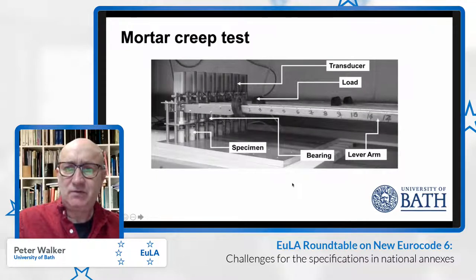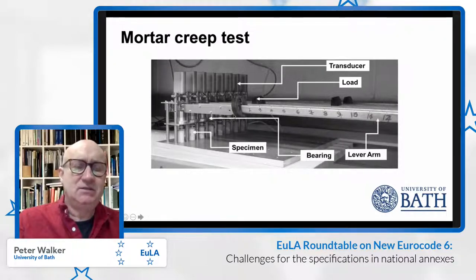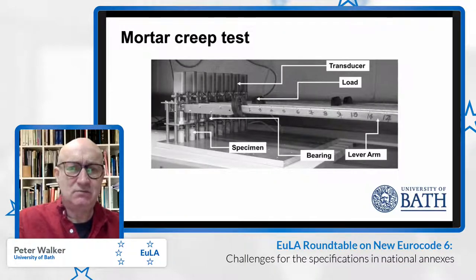And so here is the arrangement for the creep test. You can see the specimens lined up here. We could run 8 specimens simultaneously. And then we measured the change in height of the cylindrical specimens using the transducers located above them there. And the constant stress for the creep test was applied using these lever arms here. And you can see the weights, which can be moved, of course, along the lever arm to vary the stress levels. And the stresses in the mortar test were varied according to the relative strength of the mortars, because clearly some of the mortars were much stronger, as we shall see in the results, than the other mixes. So as you can see here, the weights are in some cases further along the lever arm than they are in others. And so here we would be seeing a higher force and therefore a higher stress.